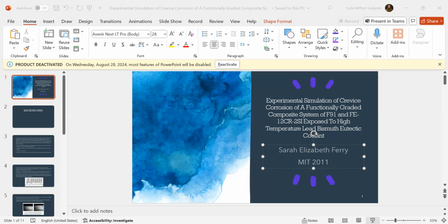The material F91 was chosen as the structural layer. F91 displays excellent radiation damage resistance, creep resistance, exhibits ductile behavior over a wide range of temperatures, and has a high Charpy impact energy. And cladding or coolant piping made primarily from F91 will thus be able to stand up to the aggressive mechanical and thermal conditions inside the LBE cooled fast reactor.